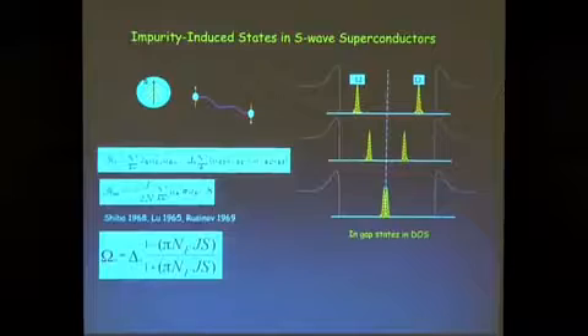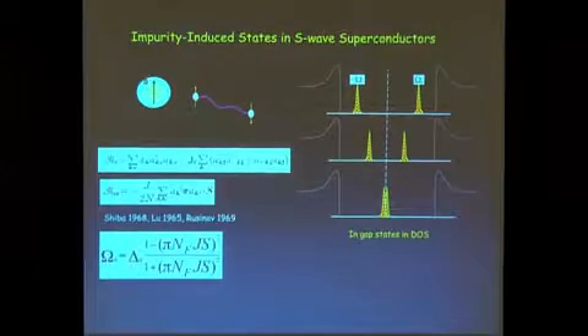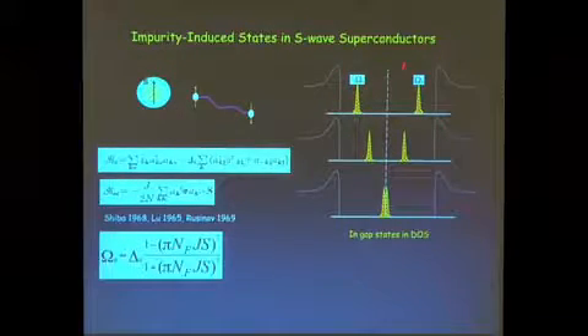More precisely, you can do a calculation where you add the exchange interaction to the BCS Hamiltonian. And when you turn the crank, you get electronic states that live at low energies inside the gap of a superconductor. These are called Shiba states. So this is the gap of the superconductor. Inside it, you get states. And where these states are in energy depends on the strength of the exchange interaction between the spin and the Cooper pairs, or the electrons, in the problem.